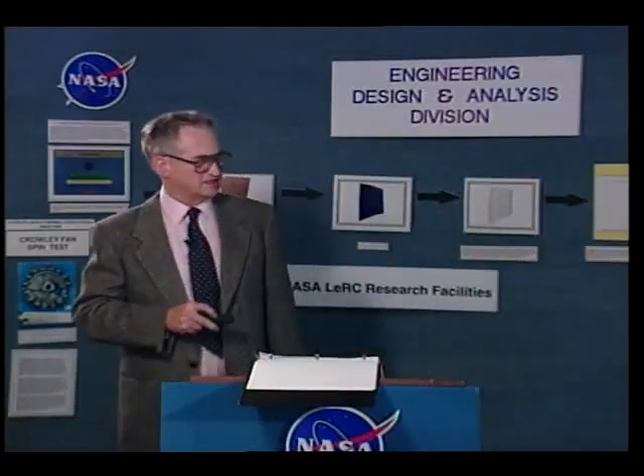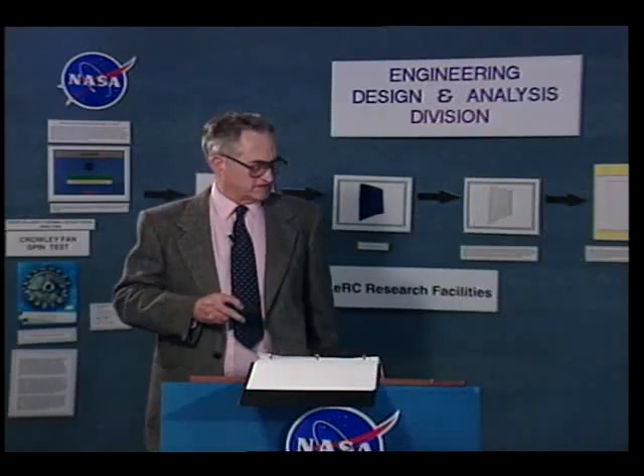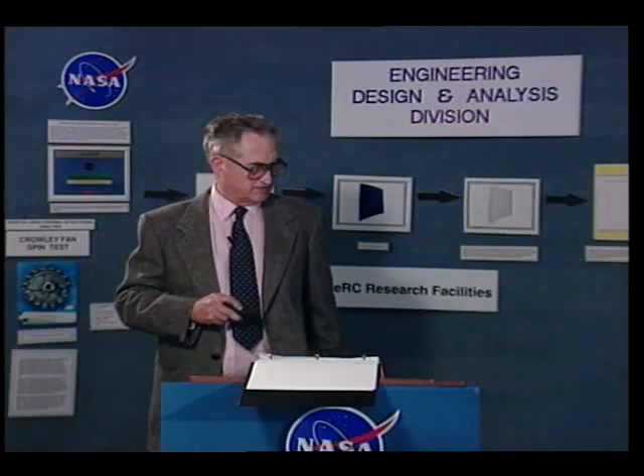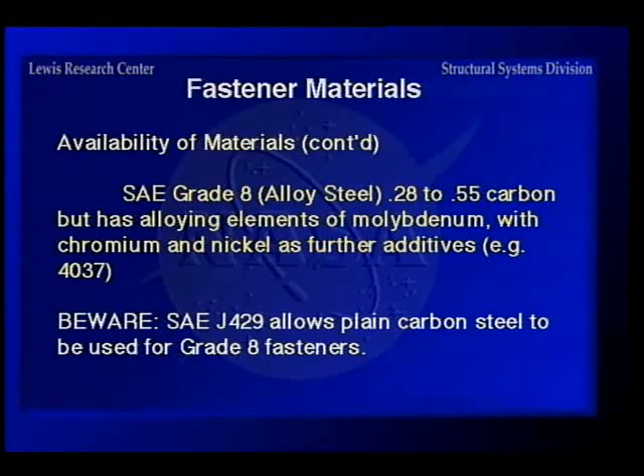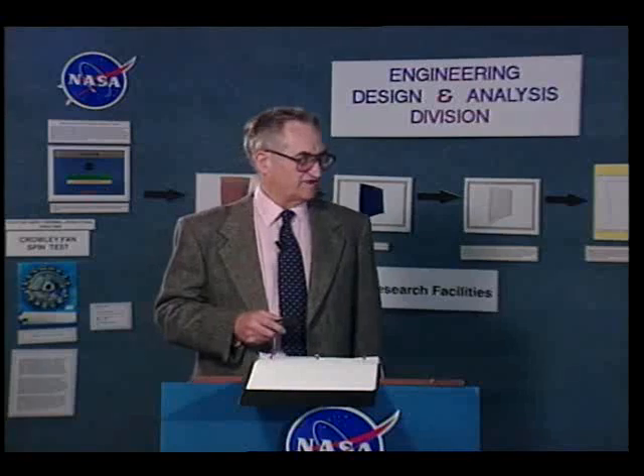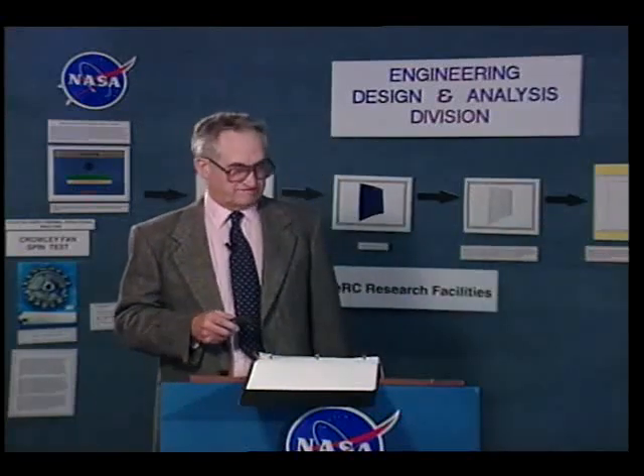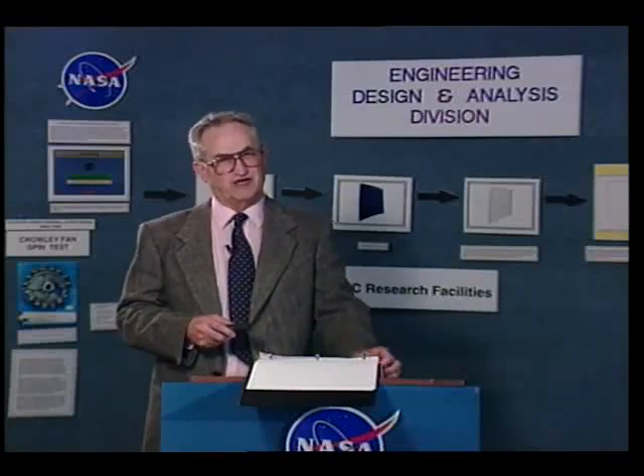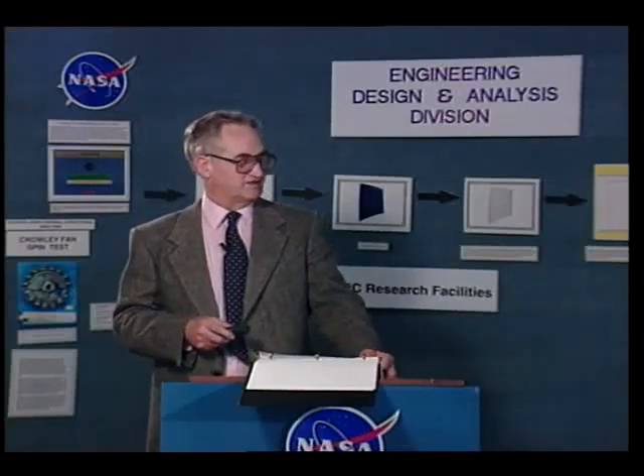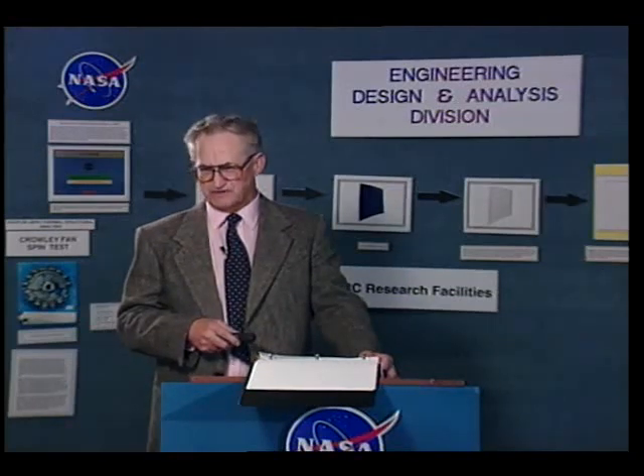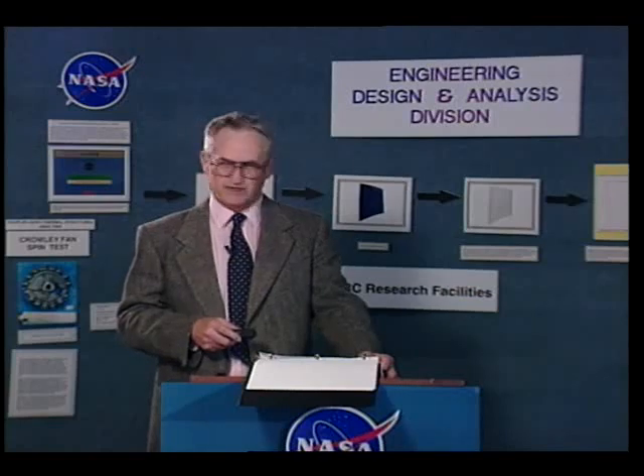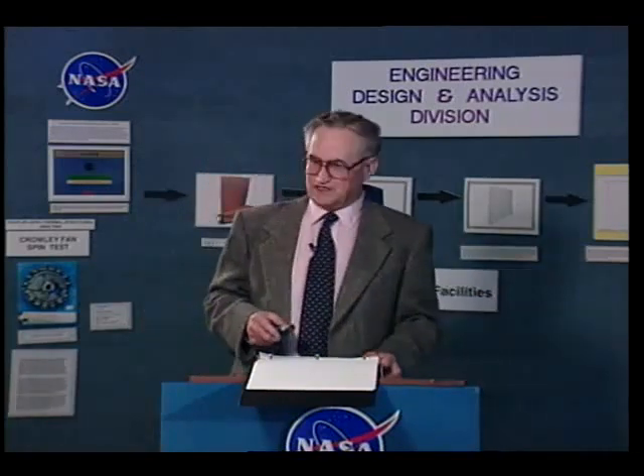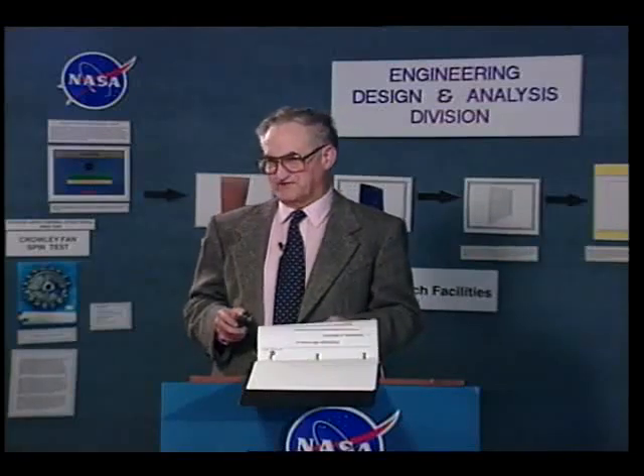Now, here's something I just wanted to point out to you. Charlie Wilson from the Industrial Fasteners Institute has been trying to get this changed for years, but it's still in the SAE J429 spec for grade 8 fasteners. There's a footnote there that allows the manufacturer to furnish these in 1045 plain carbon steel if the buyer agrees to it. Well, the only thing is, if the buyer doesn't know he's agreeing to it, he can get one that will not have very good impact resistance. And we had a problem that we were in on one time with the Army on some Abrams tanks, that when they fired the cannon, it broke the bolts on the turret because they were made out of 1045 steel.